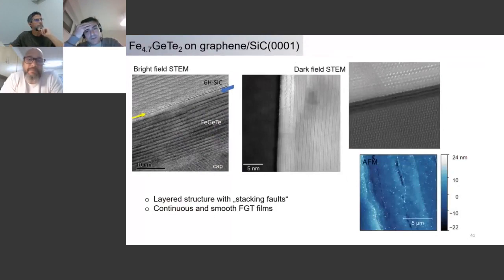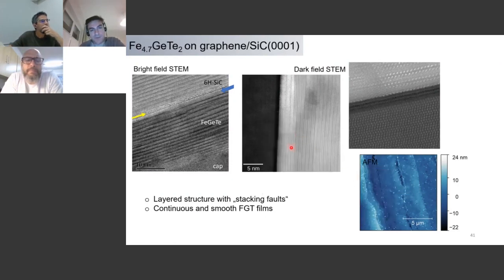Yeah, that's a very important question. Yes, we are very interested. As a matter of fact, something I did not mention here for lack of time. If we look at this image here, now dark field, let me put the laser again. It is quite interesting because what we see is that if I look at the thickness of these very first layers here, if I calculate them, they are actually thicker than what you would expect for this Fe5 material, or in reality we know we have 4.7, but they are thicker than that, and this indicates that we are actually having some what I call stacking faults, meaning we have some layers that are thicker than Fe5. They're probably Fe6 or even Fe7 germanium telluride, which are expected to have even higher TC.